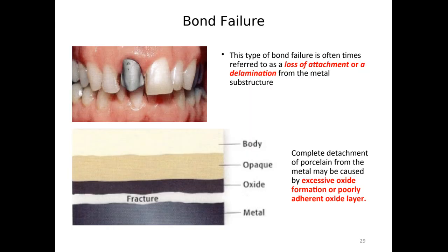This type of bond failure is often referred to as loss of attachment or a delamination from the metal substructure. A complete detachment of porcelain from the metal may be caused by excessive oxide formation or a poorly adherent oxide layer. So you see how important that oxide layer is, and how important it is to do all the preparatory steps before applying the porcelain.